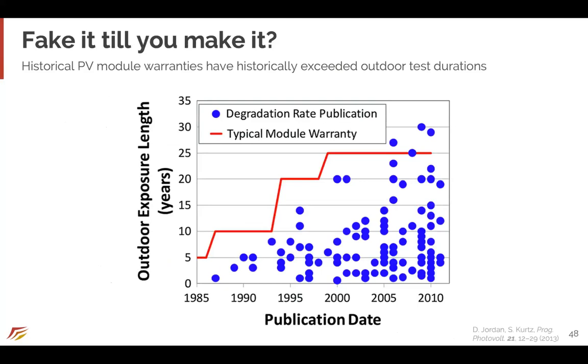Maybe a slightly different perspective. This is some nice data from a really great analysis by Dirk Jordan and Sarah Kurtz over at NREL. And it shows that historically, these are mostly silicon module warranties, have often been way out ahead, about 5 or more years longer than the longest published field tests at the time. So that's interesting. To be clear, I'm not saying anyone should go and warranty perovskites to their heart's content today. That'd be really bad for the industry. But there's some precedent for selling PV without fully proving out the warranty lifetime in the field, as long as the science is reasonably well understood.